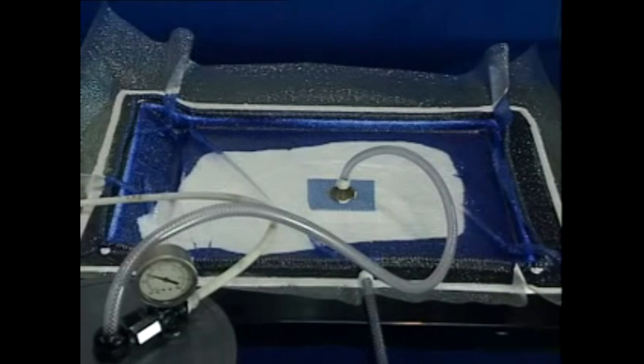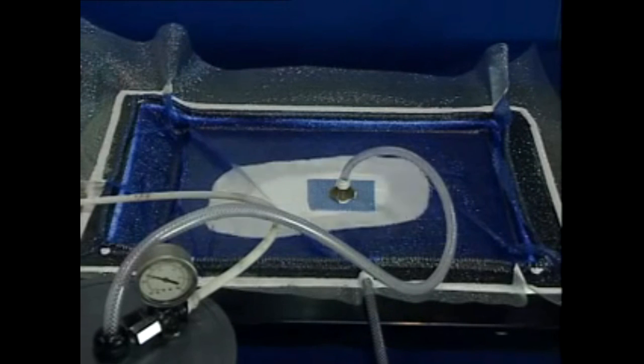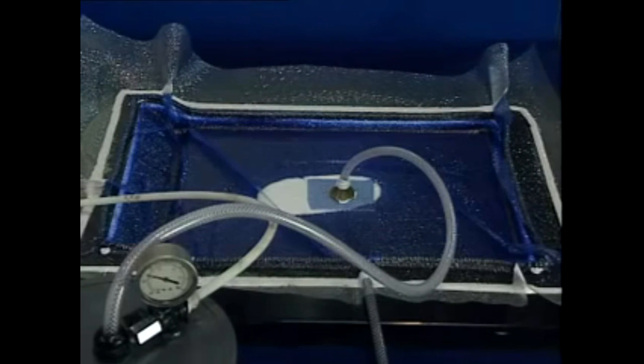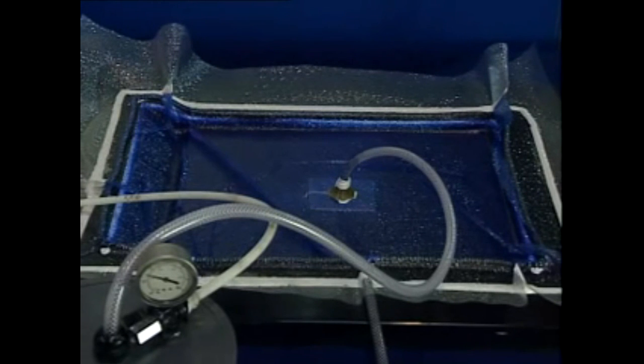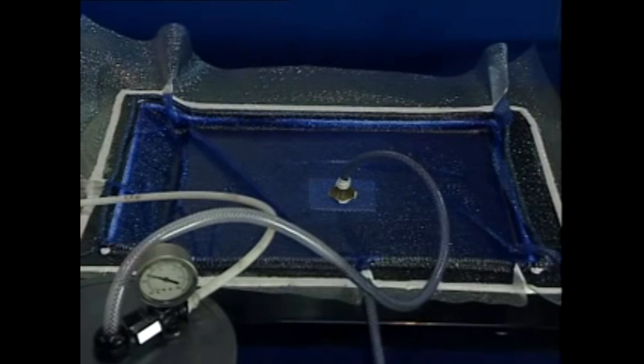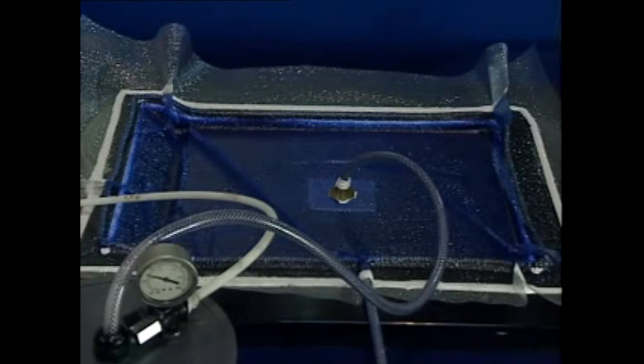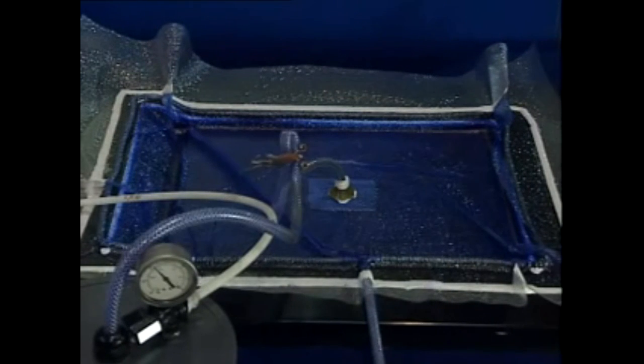This method has the advantage of quicker fill times, but the disadvantage of a greater risk of drawing air across the laminate if the bag is not sealed properly. An alternative is to feed the resin via the central hose connection and pull the vacuum from the outer channel. When full, the resin inlet is clamped. Some resin is pulled into the outlet catchpot to ensure a full air-free component. This outlet can then either be clamped or the vacuum slowly reduced to a holding level of approximately 0.3 bar.